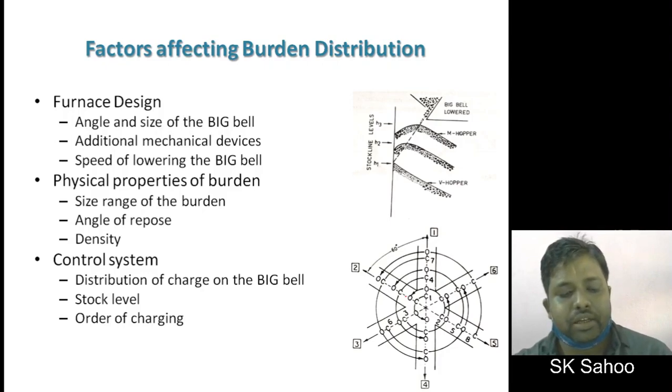We know that some dense, small and irregular particles like iron ore remain substantially where they fall, whereas light, smooth particles like coke roll into the troughs. So more clearance leads to formation of crest or peaks of fines further away from the furnace wall, and formation of M-type contour or the hopper of the stock line.